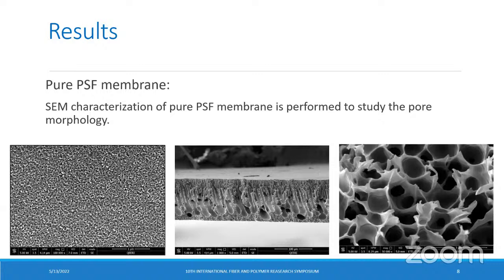The figure to the left shows the membrane pores at the top surface of the polysulfone sample, and the figure in the middle illustrates the finger-like substructure of the membrane cross-section, whereas the figure to the right shows the pores at the enlarged bottom cross-section at 3 micrometer.